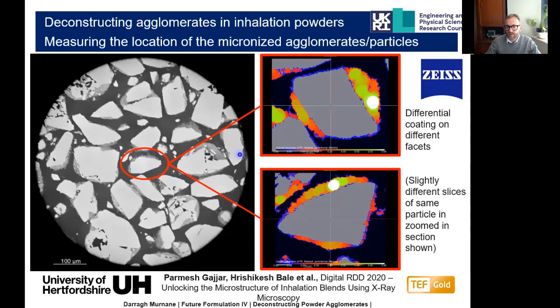And when we zoom in on those and we look at this particle from two orientations, you can see this buildup of a thick layer of micronized drug around those coating particles. And when we look at this from a different dimension, so it's the same particle to a slightly different slice, we can see that there's a really face-specific accumulation of the drug on these lactose carrier particles following the blending.